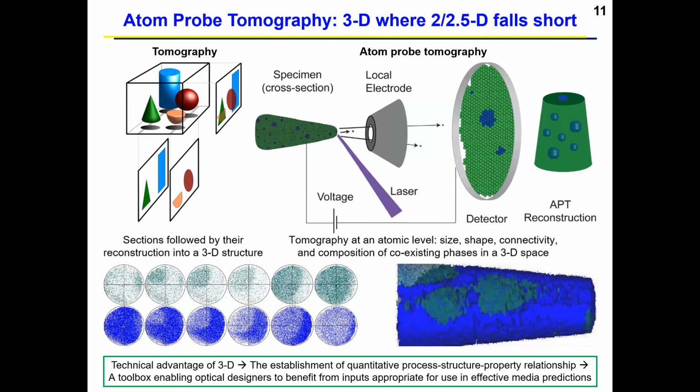Over the past 2 decades, APT has gained tremendous interest due to its ever-growing applicability to a wide range of material systems. A distinct advantage of APT is that the technique provides both high spatial resolution, less than 1 nanometer, and also high detection sensitivity, around 1 ppm, which are often the competing trade-off in other conventional micro-nano analysis.